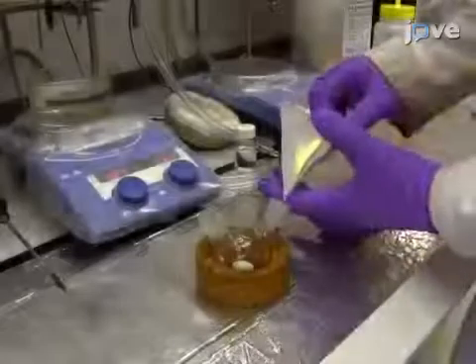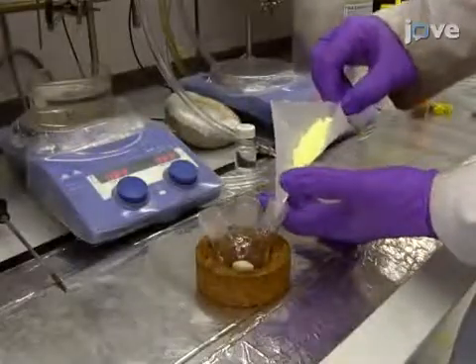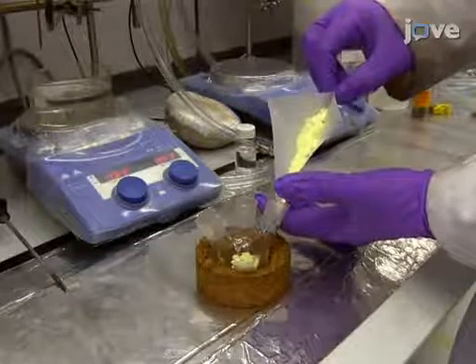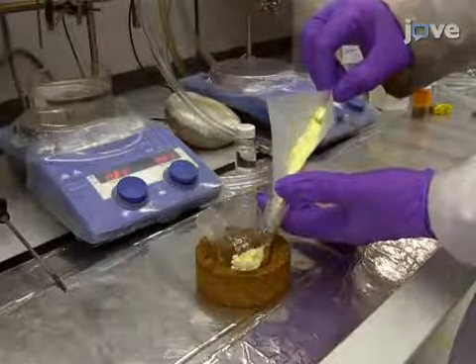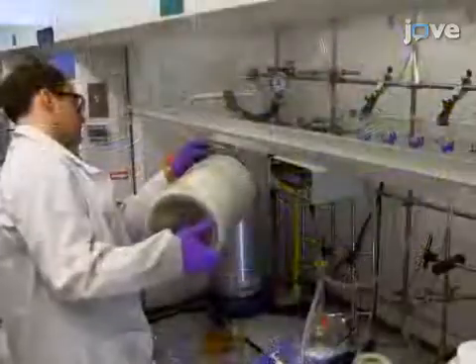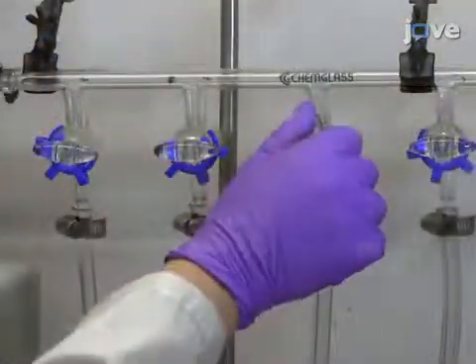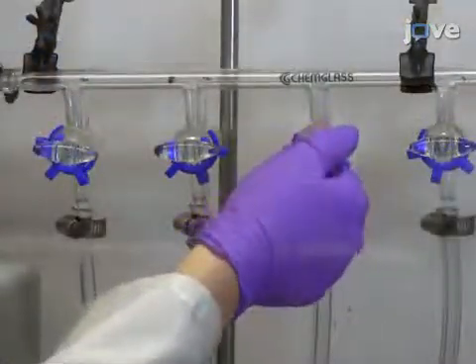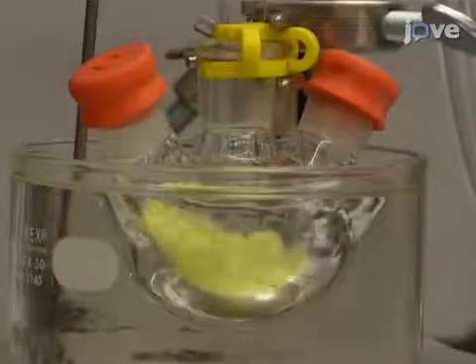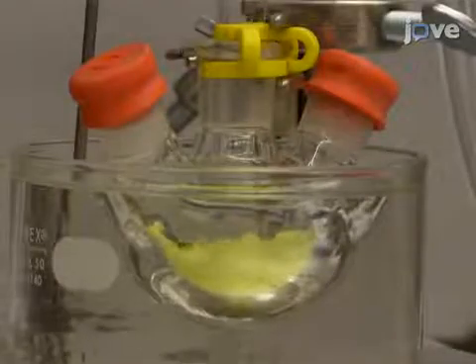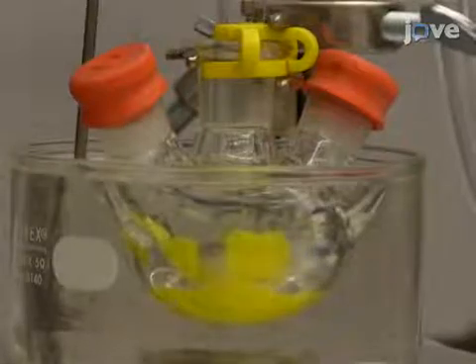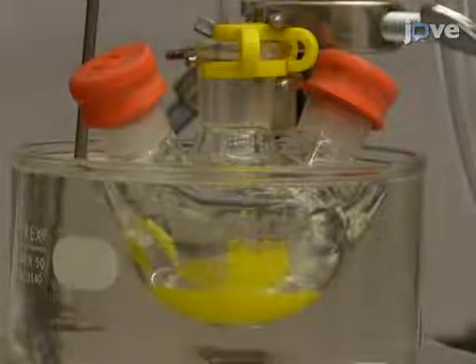To prepare the molten elemental sulfur, place elemental sulfur in a 50 ml 3-neck flask with an attached condenser and temperature probe. Perform pump and purge cycles with vacuum and nitrogen several times. Heat under nitrogen to 150 degrees Celsius with stirring. This will cause the sulfur to become a yellow-colored liquid.